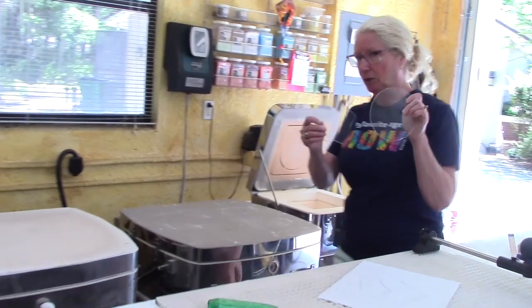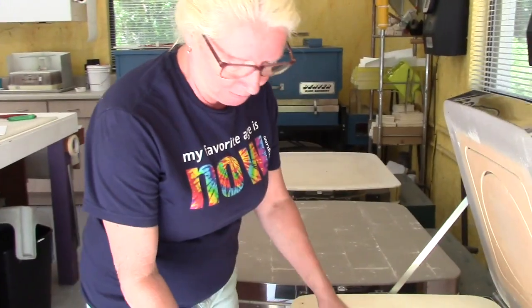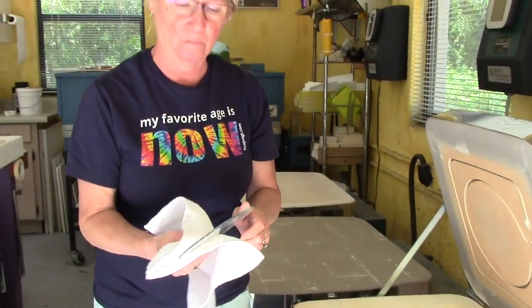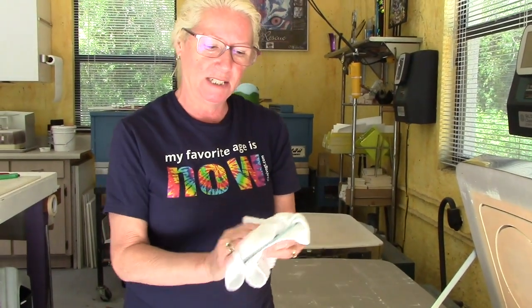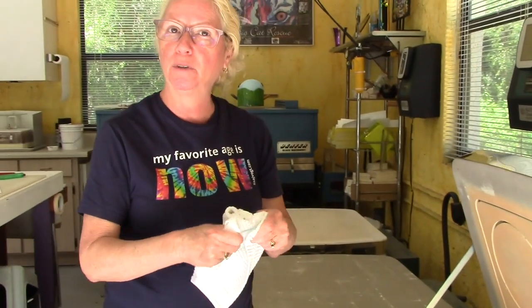Let's go over to the kiln and load these two pieces of glass. We need our molds — we're going to put these back in. This time our glass is about five and a half inches across. It's dirty from the mold dust so I'll take a dry towel to clean it. You don't have to reprime the molds — not if you're only going to 1265. Now if they show signs of wear or chipping I would prime them, and one of these is showing a little bit of chipping, but we're going to keep moving forward and stay below 1265. This primer can go all the way up to 1600 degrees and still hold up.